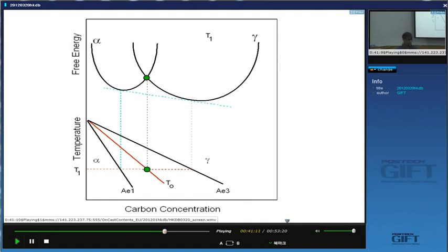Whereas, if you look at pearlite or allotriomorphic ferrite, it will grow across an austenite grain because it involves diffusion. So you've lost the connection with the original austenite in which it nucleated. But martensite only grows in the grains in which it's nucleated because it's a displacive transformation.